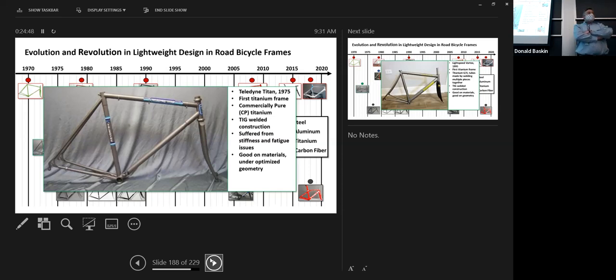So the yield strengths were really low. The ultimate strength was really low. The modulus was like two-thirds of steel, so it wasn't that stiff. They didn't really take much advantage of tube geometry. They're just basically round tubes, and they're not even that big in diameter. Okay, and so these frames were not a big success because they failed a lot and they were expensive as hell. And so titanium really didn't catch on for many years later.